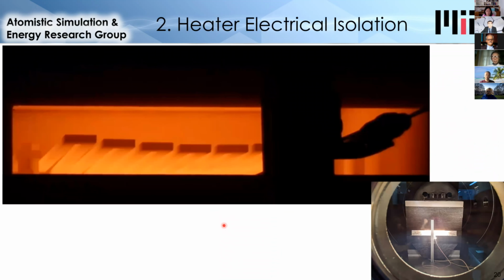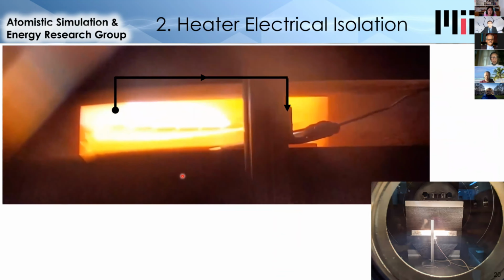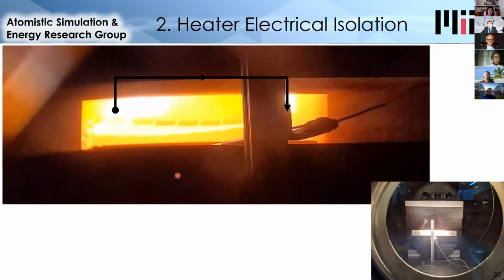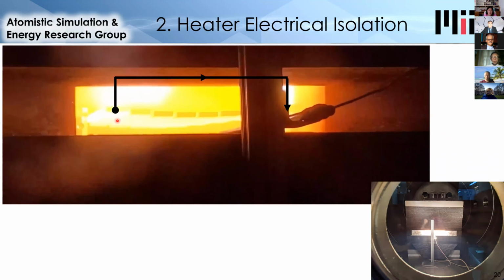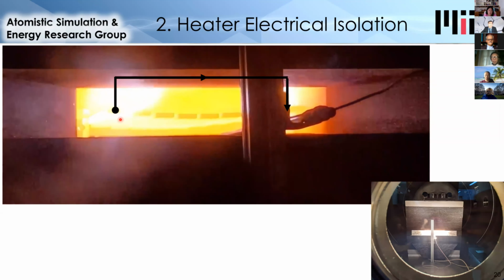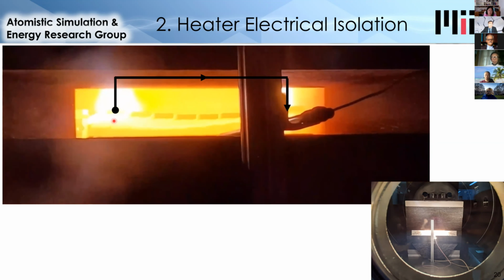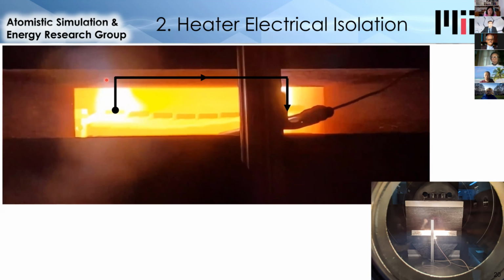And then we were able to reach higher temperatures around 2,000 Celsius when another problem occurred. And this was electricity traveling through the gas. So now there's no solids for electricity to arc through, but it actually, as you can see in this video, traveled through the argon atmosphere into the electrically conducting insulation above and then back down to the other side of the heater. The problem with this is that the resistance reduces when this happens, which reduces the heating and puts a limit on the overall temperature.